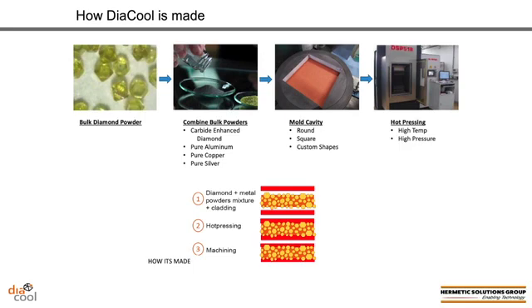The image that you see here at the bottom is just a kind of a cartoon image of how the material is put together. In step one, you'll see the matrix suspended between two layers of pure copper. So after the material is pressed and sintered into a cake, we add pure copper sheets to both sides of the substrate. And in another hot pressing step, we force that copper skin on both sides of the cake material. That's that matrix part of the substrate, and press them together to form a single bonded unit from top side to bottom side. And then in the last process step, we can machine this material to either add structures or to reduce the thickness of the copper on both sides of the substrate in order to make it more friendly to device and die attach.